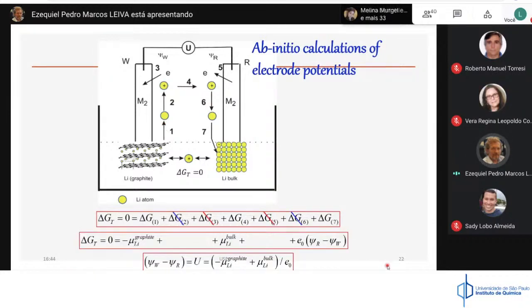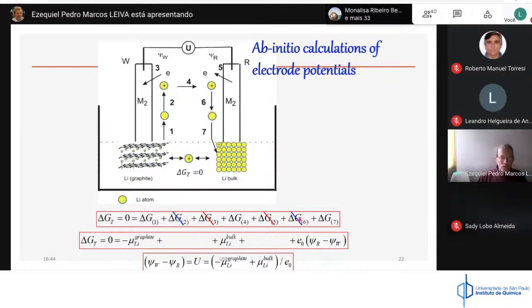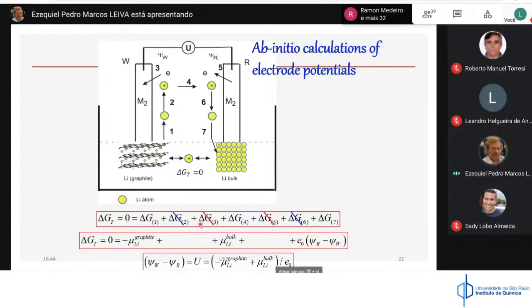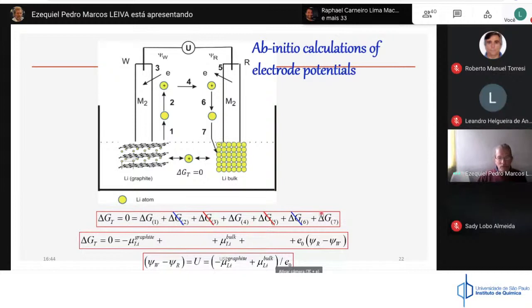The point is, if you take a closer look, some of these free energy changes compensate. For instance, this free energy 2 is compensated by this 6, so you can put them away. This free energy 3, which corresponds to putting an electron back in the electrode, is equal to the free energy change 5, but changing the sign. So these 4 terms go away, and finally you are left with 2 or 3 terms. One is the chemical potential of lithium in graphite, in this case, the chemical potential of lithium in the bulk, and the potential difference between these 2 electrodes.